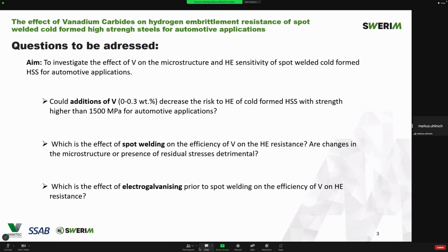In this project, we would like to investigate a bit more what happens with the microstructure and hydrogen embrittlement sensitivity of the spot welded cold formed steels for automotive applications when we add different percentages of vanadium to them. The main questions we had are: can additions of 0.15 and 0.30 weight percent of vanadium reduce the risk for hydrogen embrittlement compared to reference material with no vanadium added?